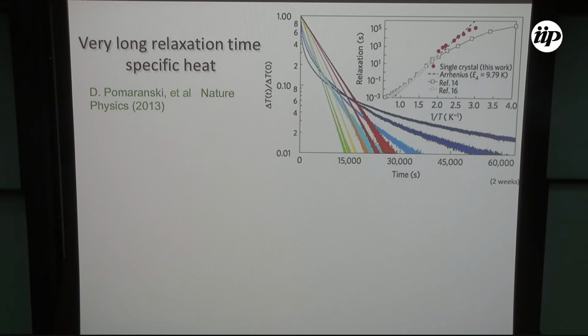So that's what these people did. This is work by Pomaransky and collaborators. This is the work of Kycia, also in Waterloo. This is an experimental work. So what they did was to say, okay, if we need to wait, we'll wait. And they measured specific heat. And you see here, this is the relaxation time measured in seconds. But you see that essentially for some of these curves, you have to wait for 2 weeks.